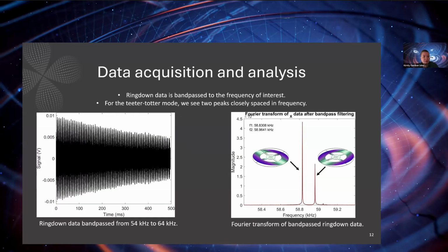So here is some example data. On the left-hand side, I'm showing what we call a ring down. It's how the displacement of the disk changes over time. So you can see this decay over time. And you'll see in the time series data on the left that there's this interesting beat frequency. That's because the mode that we're measuring at the moment is this teeter-totter mode of the microdisk, which I've shown images of on the right-hand side.